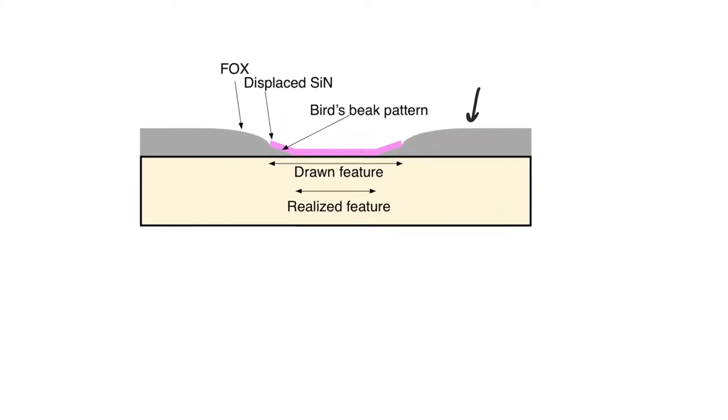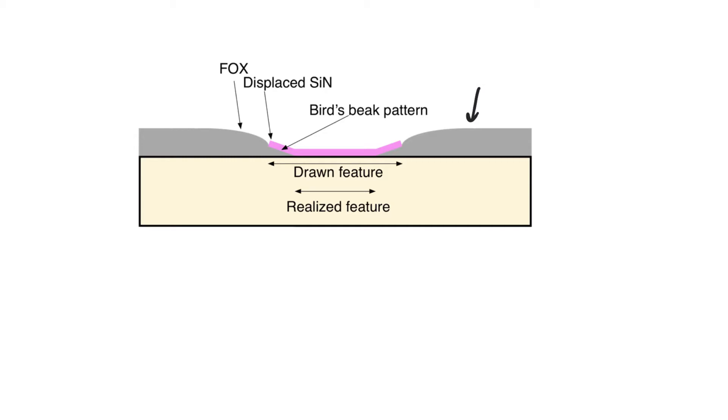Field oxide is going to be effective at separating transistors from each other when it has grown to a very high thickness. But there is a problem when we start to form field oxide. Remember that we are using silicon nitride to protect the areas that will have thin oxide from oxidation. And so the more we try to oxidize the substrate and the thicker the oxide gets, the more it starts to oxidize below the nitride, causing it to lift.